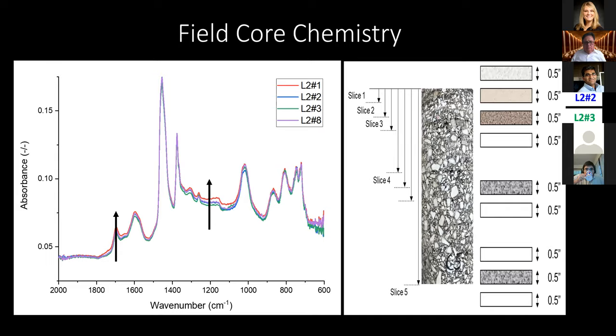The next graph shows the FTIR spectra of that extracted binder at those lifts. The purple is the furthest down. It's the number 8 slice. L2 is the green as you move up towards the surface. The next line is L2, number 2, getting closer to the surface. And the L2, number 1, is the red curve. And you can see with the arrows that the oxidation is greater. And we can see those indices would be higher at that higher surface. So the more aging is at the surface of the binder, but there is still some aging seen throughout.